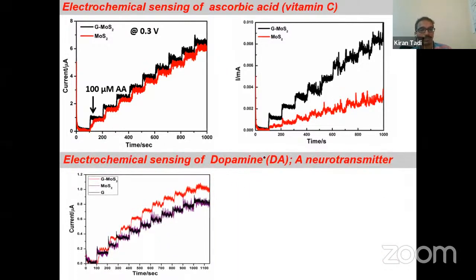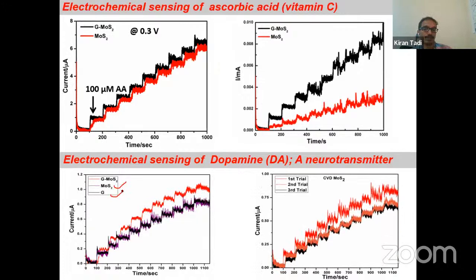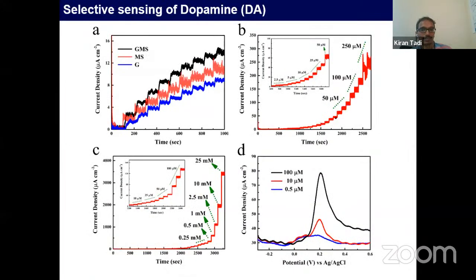For dopamine, which is a neurotransmitter, graphene-MoS2 shows the highest sensitivity compared to MoS2 and graphene alone. Across first, second and third trials, the sensitivity signal gets reduced in the case of MoS2 alone, but in the case of graphene-MoS2, we found very stable sensitivity here.